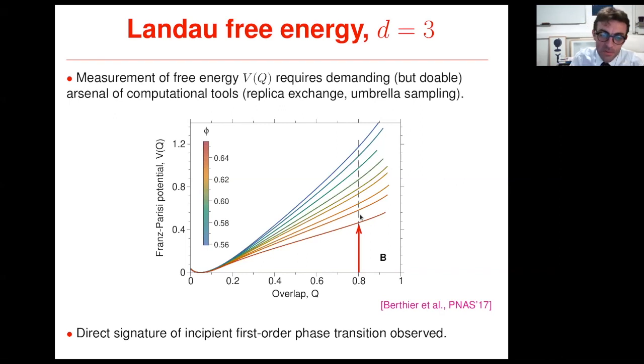So we remain above the glass transition, but we approach it considerably closer than before. So what these data reveal is essentially the development at large overlap of this metastable glass phase that was predicted in the theoretical pictures I mentioned before at low temperature. So this type of study represents, in a sense, the direct signature of this coming first order phase transition that is predicted by the mean field theory. This transition between the liquid and the glass at large Q values here.